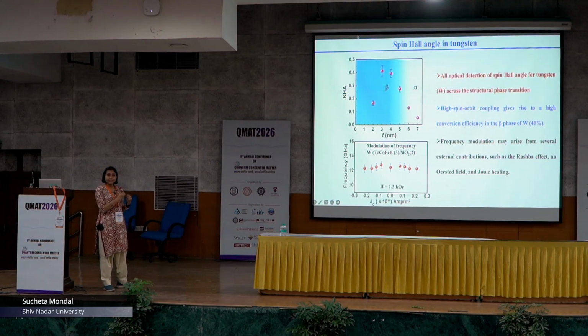The drop simply means an underestimation of spin Hall angle for that particular thickness, because when we have two layers coupled, there is also another important term that you have to keep in mind, which is spin diffusion length. Spin diffusion length for tungsten falls in the regime of 2 to 3 nanometer. So this regime is suffering from backflow, that is why there is an underestimation. The highest spin torque efficiency or spin Hall angle we have obtained in this system is about 40%, which means 40% of the charge current can be converted into spin current, which was moderately high if we compare publications at that time.